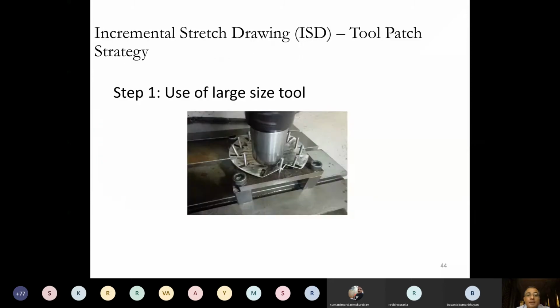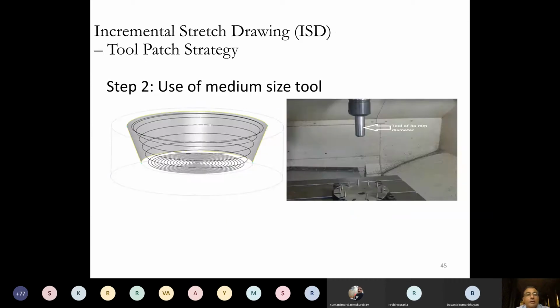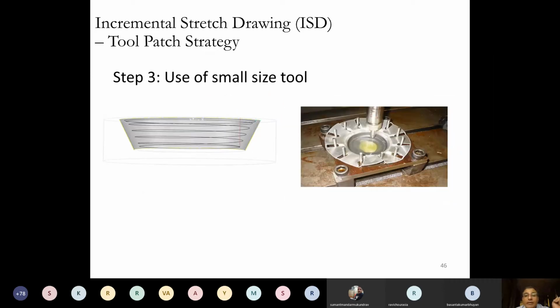And now I'll show the three stages. This is a drawing operation which was done with the help of a large tool. Then we used a medium-sized tool of 30 mm diameter, with the tool path from inside to out, and it was meant for both drawing as well as incremental sheet forming. Then we used a smaller tool of 13 mm diameter, where it was pure incremental sheet forming, and this led to the formation of this geometry.